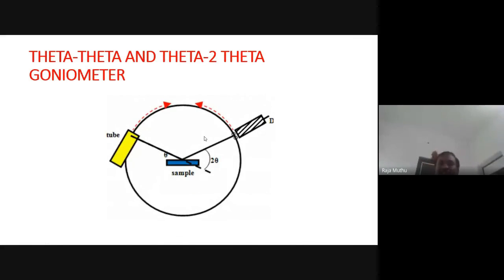In the theta-2theta goniometer, the tube is fixed, whereas the sample and detector can move. The sample moves with velocity theta, whereas the detector moves with velocity 2 theta. This is the theta-2theta goniometer. I repeat: in the theta-theta goniometer, the sample is fixed and the tube and detector move with theta, whereas in the theta-2theta goniometer, the X-ray tube is fixed, the sample moves with theta and the detector moves with 2 theta.